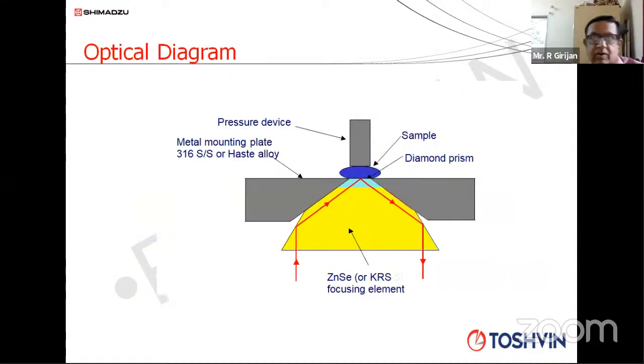Why diamond ATR is required is, as I told you in the beginning, for IR analysis you should know the hardness and physical properties of the sample. There can be some very hard samples, like a polymer bead. You cannot ensure proper contact between the sample and the prism because it is a circular bead. You have to really press it to create a proper contact. But because the material is so hard, your crystal will break. If you apply pressure, zinc selenide or germanium or KRS5, these are all light crystals, they will break. So you cannot use those types of crystals.